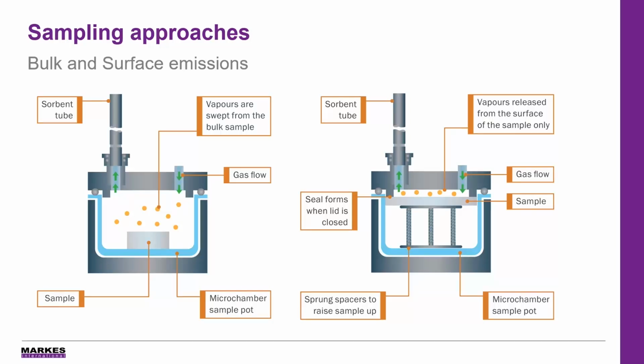Now, flat or planar materials can be cut to a specific diameter of 64 millimeters and placed on spacers that allow us to accommodate for materials of different thicknesses. These samples are then raised up in the system so the lid closes down directly on the surface, creating a surface-only emission parameter. The emissions from these are calculated in micrograms per meter squared per hour and then can be extrapolated to predict the emission rate of larger samples.